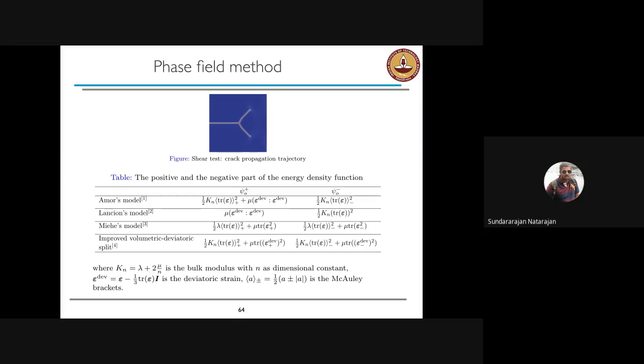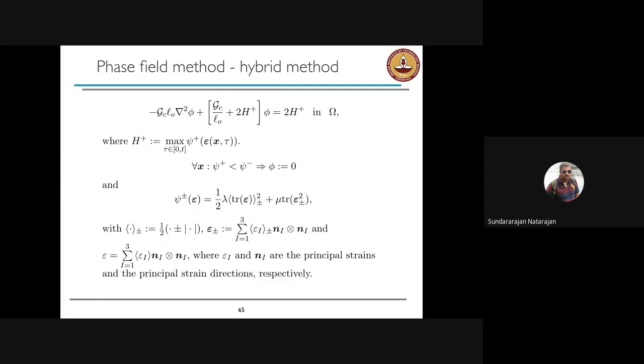This was because the earlier model allowed the crack to grow also in the region where there is a compressive state of stress, which is not physical. There has been a lot of work to avoid it. There have been approaches like additive decomposition of the strain into deviatoric and volumetric parts, and decomposition based on eigenstrain, which suppresses the crack growing in the compressive region. That's the formulation behind it, where you update the history variable only with the positive side, or only the tensile part of the energy, whereas the negative side you just ignore, so that the crack doesn't grow on the negative side.